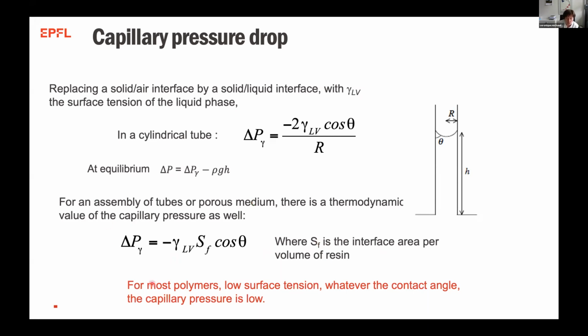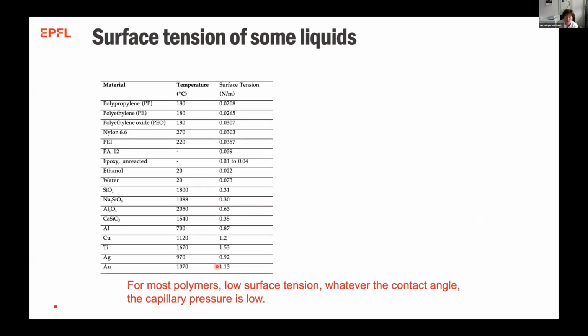So as you see in polymers, first of all, if cos theta is positive, delta P gamma is negative, and it's a wetting case. And the more interface area you have, the more capillary pressure you should get if it wets, which is interesting. But it also depends very much on this gamma LV, the surface tension. For polymers, the surface tension is typically very low compared, for example, to metals, molten ceramics, or water, which is here, or ethanol. We're about in the range of ethanol. So it's rather low surface tension. Whatever cosine theta is, you will have a small effect due to the surface tension.